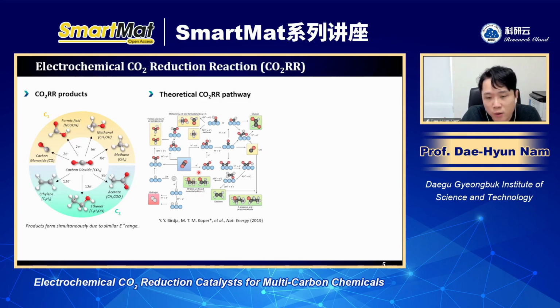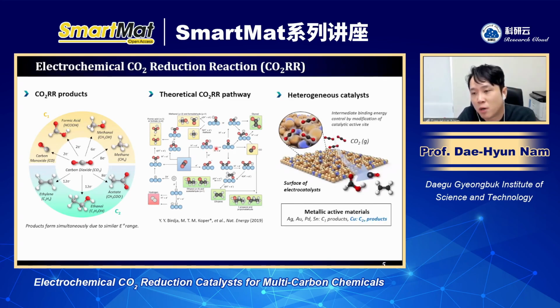If you look at this diagram, it looks very complicated. The way we can control or steer the pathway is to develop a catalyst which can control the binding energy between the intermediate and the catalyst surface. For this purpose, people are developing heterogeneous catalysts to control the intermediate binding energy by modification of these catalytic active sites.